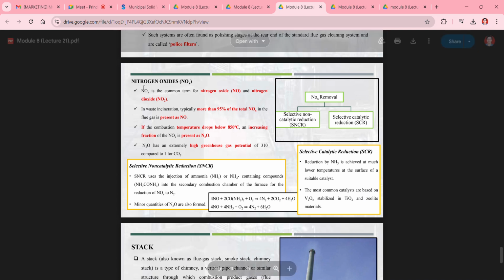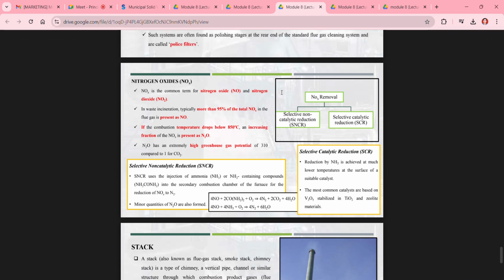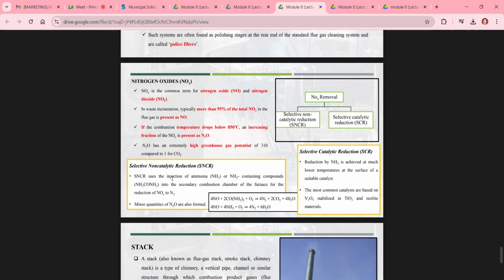And NOx removal: NOx is the common term for nitrogen oxide and nitrogen dioxide in waste incineration plants. More than 95% of the total NOx in the flue gas is present as NO. If the combustion process drops below 850 degrees Celsius, an increasing fraction of NOx is present as N2O. N2O has an extremely high greenhouse gas potential of 310 compared to 1 for CO2. That NO or N2O has to be converted into nitrogen with the help of a suitable environment during the flue gas treatment processes.